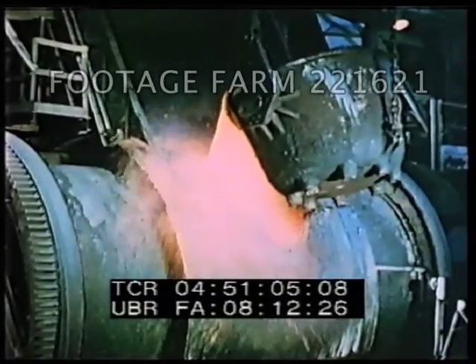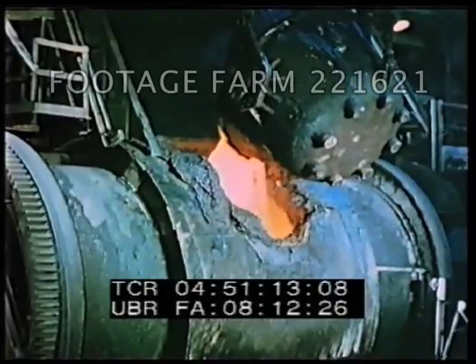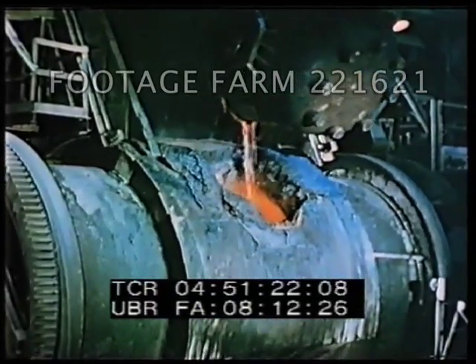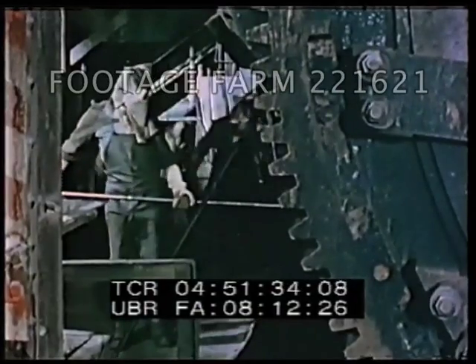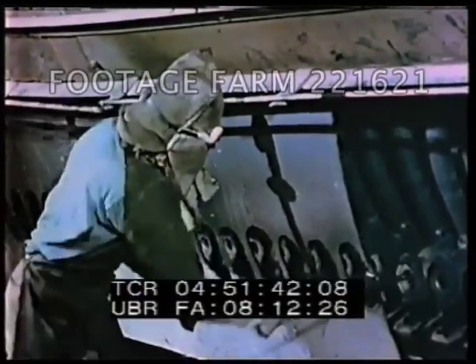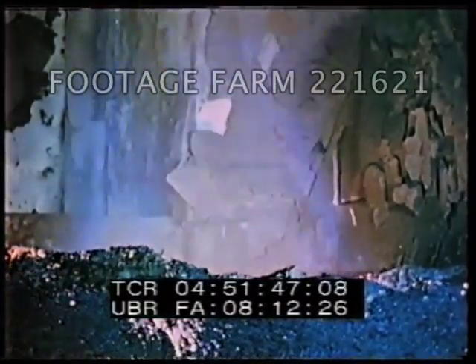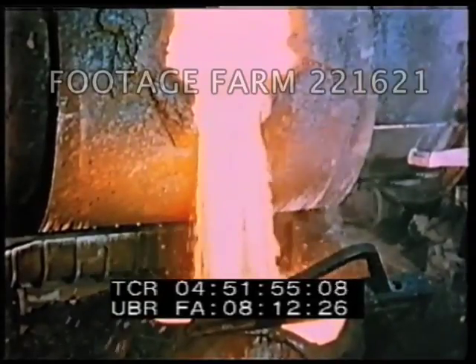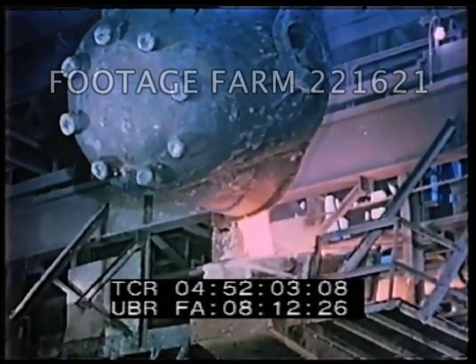The matte is then carried to another furnace, known as a converter. In the converter, the iron and sulfur content of the matte is removed by additional processes. One important step is the forcing of compressed air through the molten mass. Men protected by hoods from flying bits of hot metal keep the air ducts open by frequent punching. The air helps to burn off the sulfur and change the iron to slag. The slag formed in the converter contains some copper and is therefore collected and returned to reverberatory furnaces to recover as much copper as possible.